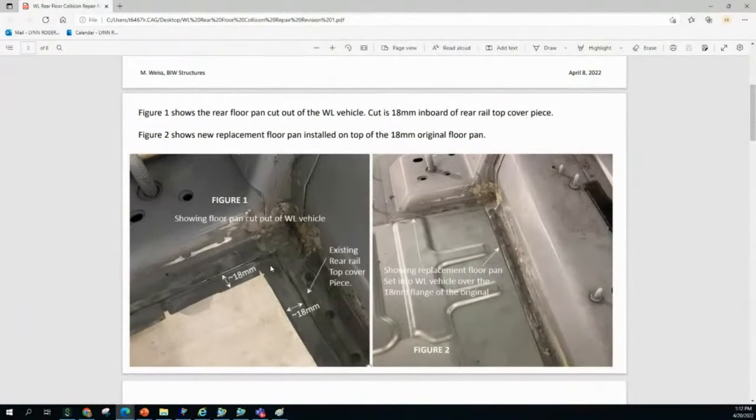And so I want to touch on that. When we make a recommendation, and if you have gone into service library, for instance, to replace a frame rail on the new Grand Cherokee front, we've got pretty explicit directions in there on how to do that for changing out the shock tower area. If you read through that, it'll talk a little bit about weld through primers and so forth. One of the things that can be unfortunate is the name weld through primer. What we don't want you to do is weld through it, right? We want to make sure that you're actually welding to that parent metal, so we want to make sure that area is cleaned out.